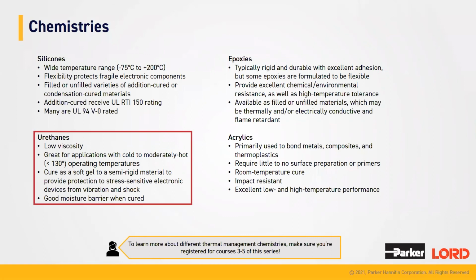Moving to urethanes, urethanes are generally very low viscosity materials that are great for applications with cold to moderately hot operating temperatures. Typically, these materials will cure to anywhere from a soft gel to a semi-rigid material that can still provide protection to stress-sensitive electronic devices because they do still retain some flexibility even in their semi-rigid state. Also, generally, urethanes, when cured, are a very good moisture barrier.